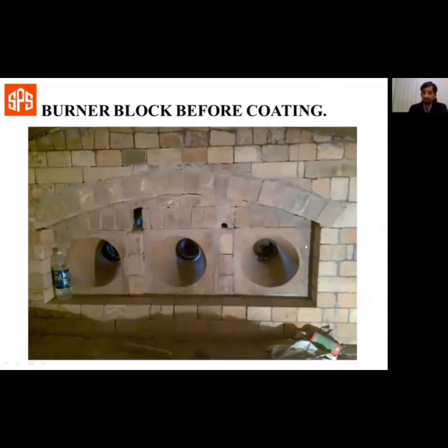This is a new refractory lining that you'll see. The masons usually have a habit of applying some local putty that neither has high heat resistance nor good adherence. And this is the reason most of you may have noticed the amount of time and fuel taken by a furnace to achieve the temperature of 1250 degrees only increases with time. A newly relined furnace will take lesser time and fuel as compared with the same furnace, say after 6 months. The reason being thermal shocks and cracks of refractory. Another important indicator, the furnace outer shell too becomes hotter as months pass by.